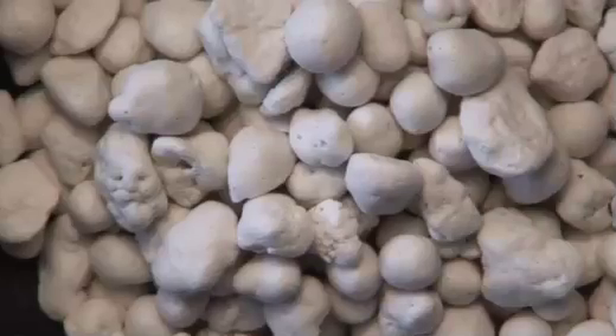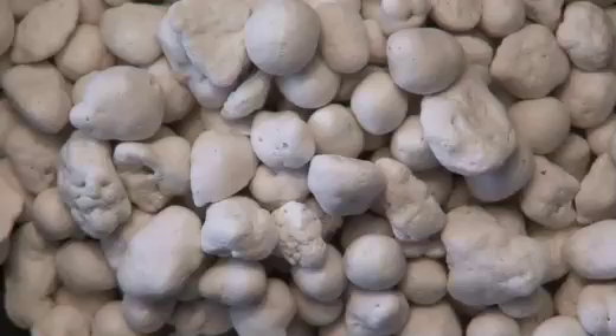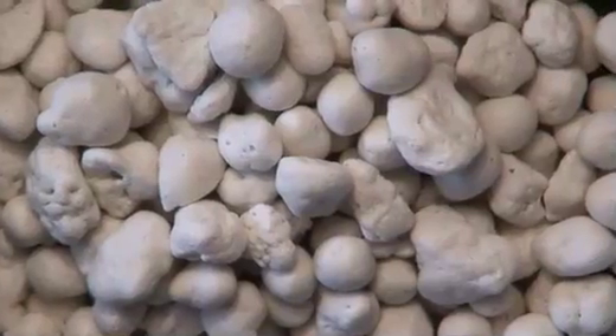For the exact same reason, a lot of applicators, a lot of manufacturers try to add, let's say, foaming agents, at least 4%, minimum 4%, in order to try to avoid freeze-thaw in the northern climates. The issue is, if you're manufacturing by trying to consolidate the concrete, then you can absolutely not use foam, because you would degrade the foam bubbles. The beauty of this product, again, is it's a multicellular structure. So if you have water entering cement, as we all know, water gets absorbed into cement over time, you would have the crystals of water expand and enter the bead, and it would not fracture the interior of the cement, and you will not get delamination occurring.